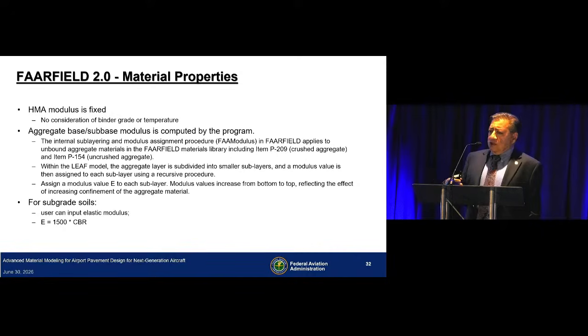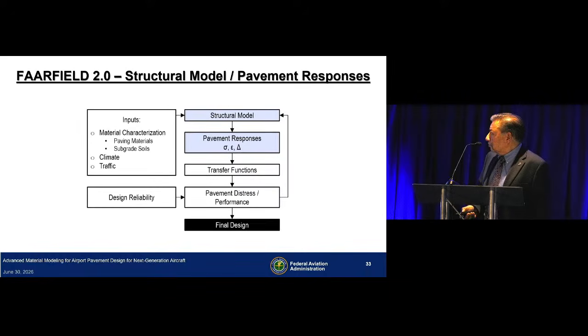For subgrade soils, the users can input elastic modulus, but most of the time CBR is the value that is available, and CBR is converted into modulus by multiplying it by 1500. That also raises some issues, because if you look at the relationship between modulus and CBR in the literature, there is a wide variation in those modulus values. So which relationship do you really use? The one that FAA uses comes from the Shell design procedure, 1500 times CBR.